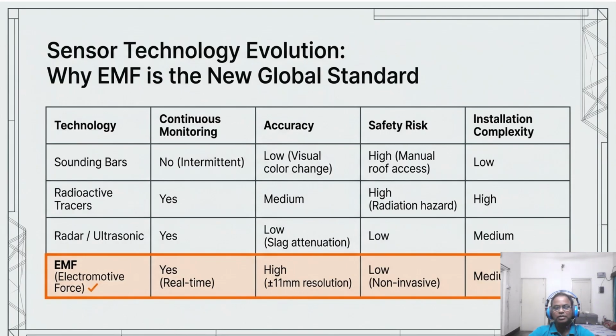So this is the core concept. The blast furnace hearth is actually a giant chemical engine. As you can see, the reduction reaction near the interface of the hot metal and slag generates a natural voltage. We also capitalize on the conductivity gap. Molten iron is a superior conductor. It acts as a short circuit, while slag is a million times more resistive. As the iron level rises, it shunts out more of the resistive lining, and we measure that change as a shifting voltage on the outer steel shell.